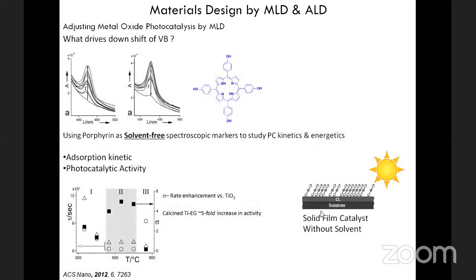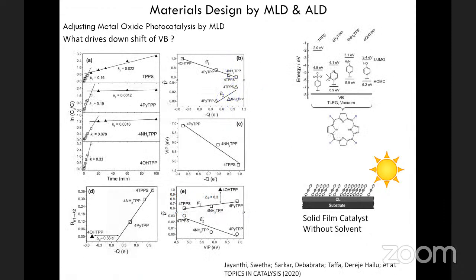And then we also wanted to do some experiments where we do it in a solvent-free environment, meaning we take the photocatalytic films, we bind spectroscopic markers, which are porphyrins, and we study the degradation, as you can see here, by following spectroscopically the Soret band of these molecules as a function of irradiation time. And all of this is done with no solvent. So we can only quantify the pure electronic effects by varying the porphyrins. And we did it for 4 porphyrins with different substituents here.